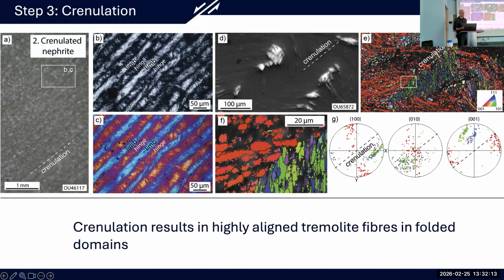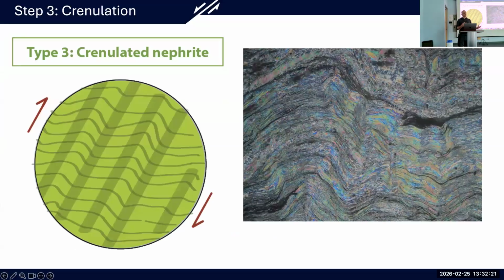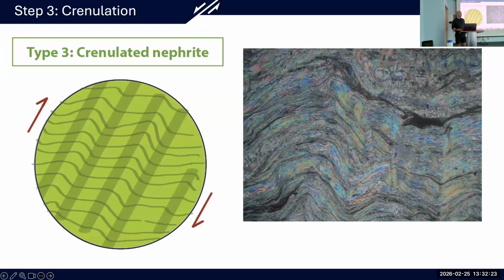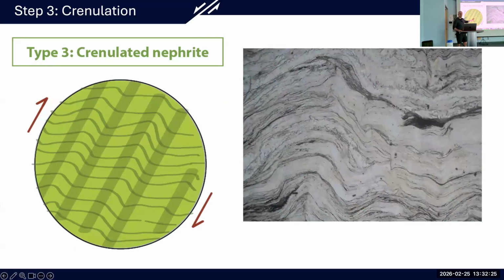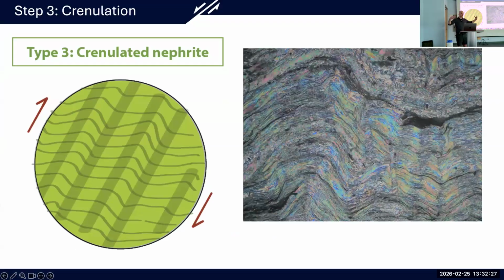And so this gives us highly aligned tremolite needles in folded domains throughout the rock. This gives us our third type. Now, if we sustain those conditions that are forming that crenulation, that are compressing it, eventually this is going to reorient itself fully and turn back into a schistose rock. So the schistosity will simply be vertical as all those needles compress and reorient themselves with that stress field.